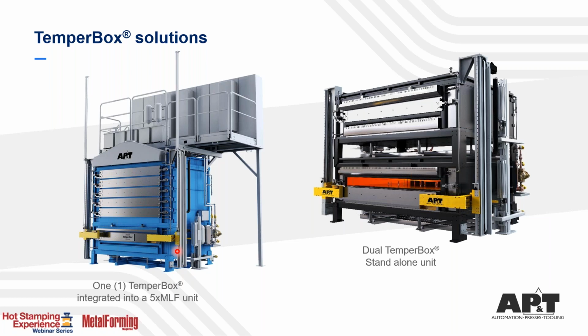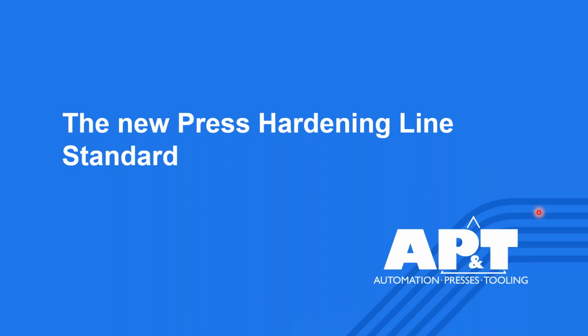Typically, you will also see that in one of the next slides, we would use 4 of these towers in a press hardening line, but we can also add a 2-chamber temper box to, for example, roller hearth furnaces, lines with roller hearth furnaces. Doesn't matter if it's a 90-degree or an L-shaped line or a straight line. And typically, we would also use 2 of these towers so that we have 4 temper box chambers that we can use during the press hardening cycle.